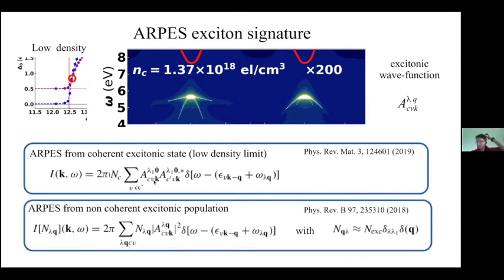There is a small difference in the non-coherent case: here you have just the summation over one conduction band index, while in the coherent case there are two different indices. The signal from these two equations is exactly the same if one takes a thermal state population peaked at the specific excitonic state — this is discussed in a paper by Kemper. This kind of signal has been recently measured by at least two experimental groups. One is the group of Ralf Ernstorfer: they show time-resolved ARPES measurements on bulk WSe₂, pumping resonant to the excitonic state in one case and above the band gap injecting electrons in another. They take the signal in k-space and Fourier transform it to get the excitonic wave function, since the signal is proportional to the square modulus of the excitonic wave function. A similar experiment was done by the group of Keshav Dani on monolayer WSe₂, which has a bigger binding energy so they can better resolve the distance between the excitonic signal and the conduction band.